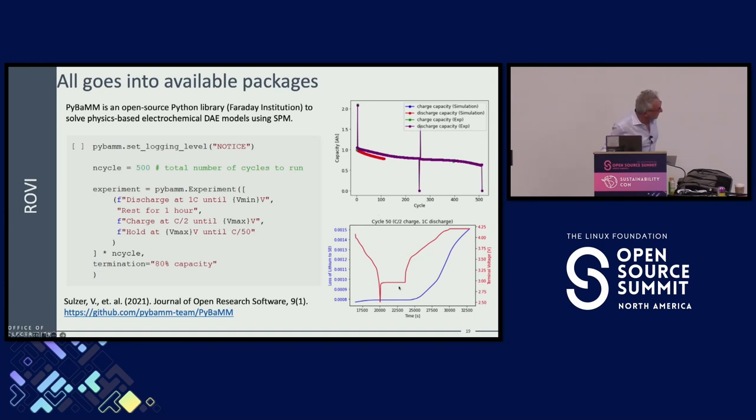And then one can start doing things like, oh, look at that. If you look at this plot, the blue curve is a measure of degradation. And then you say, okay, fine, this lithium battery under this condition is not degrading during discharge, it's mostly degrading during charge. So now you can go back and say, how do I charge this thing? Which is one of the reasons why your iPhone is becoming a little bit more particular on how you charge.